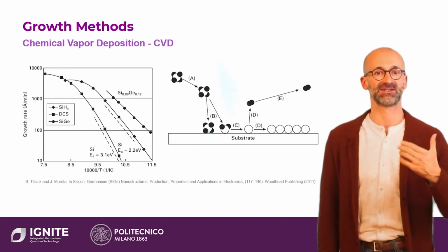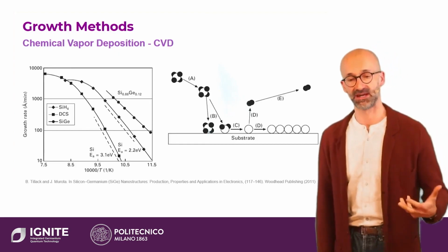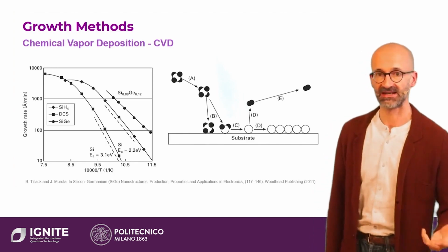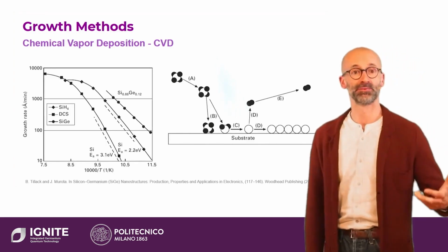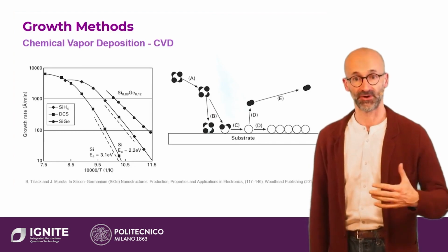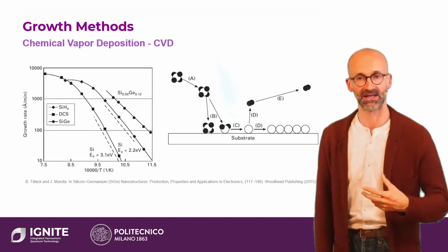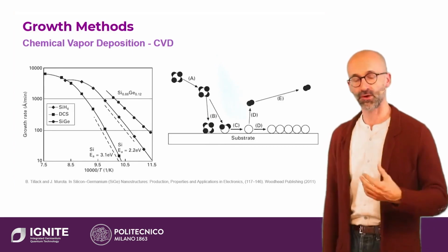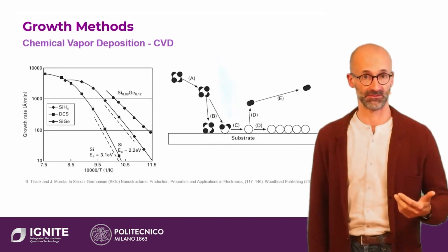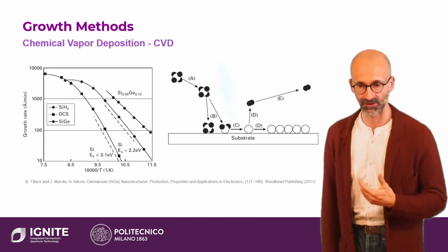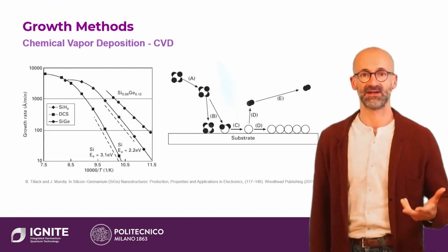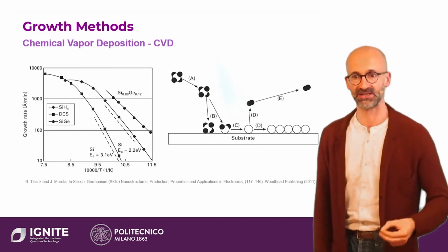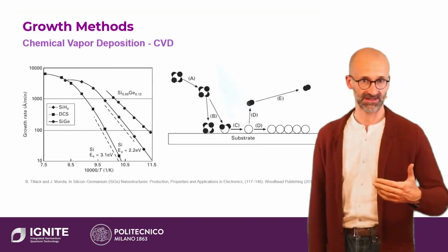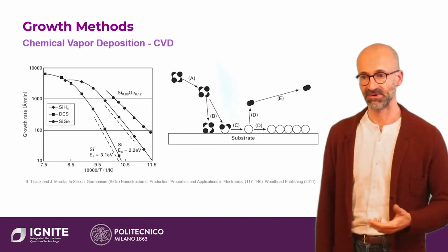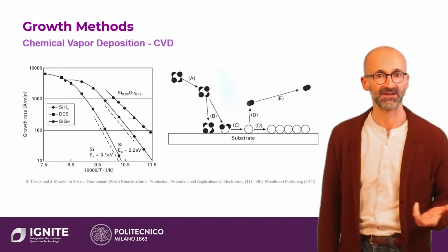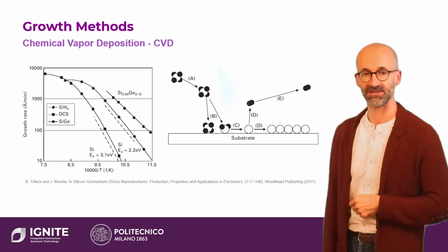The drawback is that there is a strong dependence between the substrate temperature and the growth rate. And in the case that, as we saw, you need a low temperature to grow these silicon germanium structures with pure germanium channels in order to avoid relaxation and interdiffusion, to grow at such low temperatures means the growth is going to be very slow. And then in order to optimize the graded buffer, or the reverse graded buffer, there's a strong trade-off between the temperature of the growth, where a higher temperature means these thicker layers grow more quickly, but a lower temperature may be needed in order to optimize the defect structure or the roughness of the material.